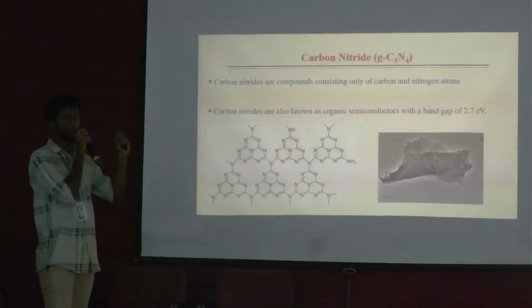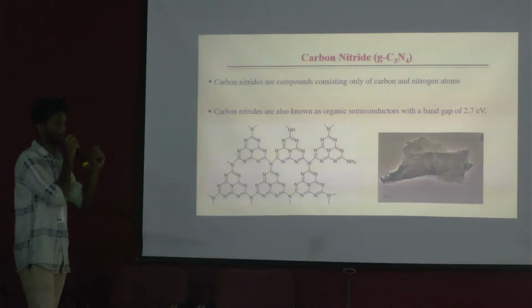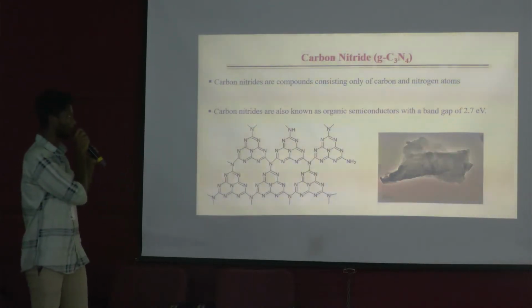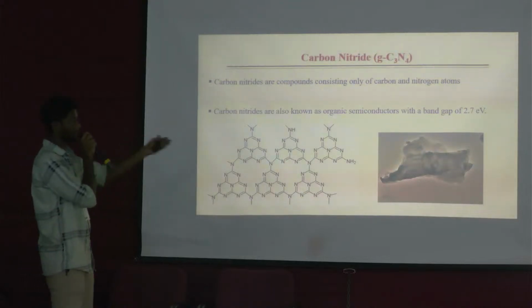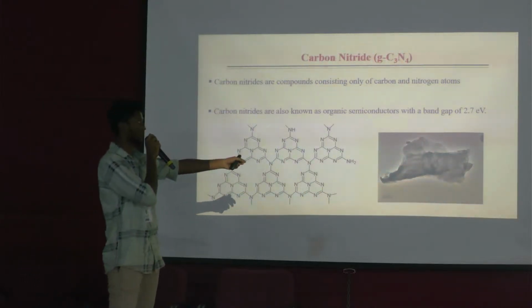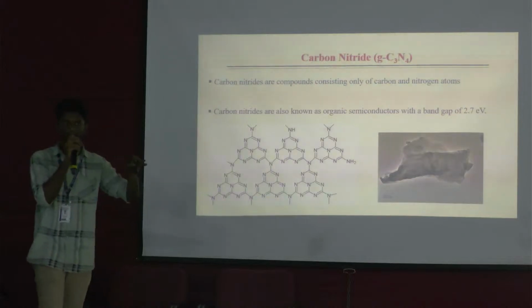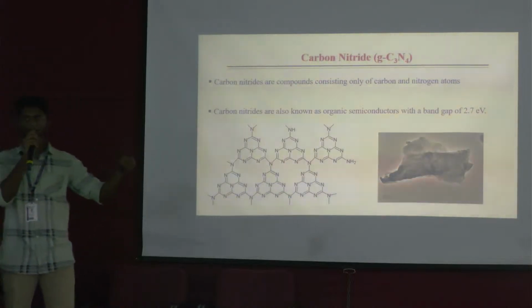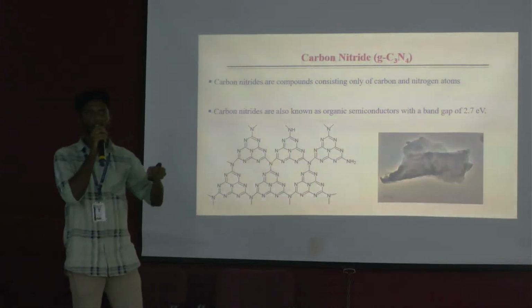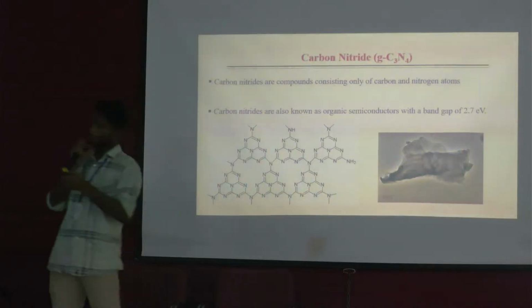Carbon nitride is also known as an organic semiconductor with a band gap of 2.7 electron volt. It is like a polymer structure. This is an SEM image of the graphitic carbon nitride. It is like a layered structure. From SEM, we can analyze the structural morphology of our compound.